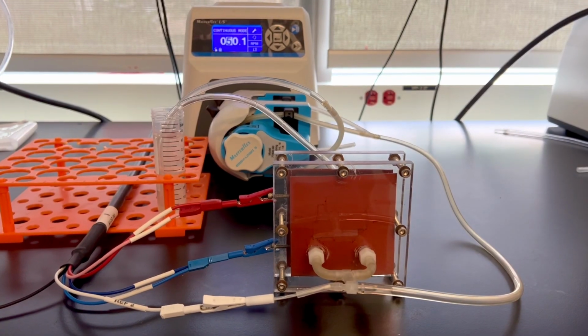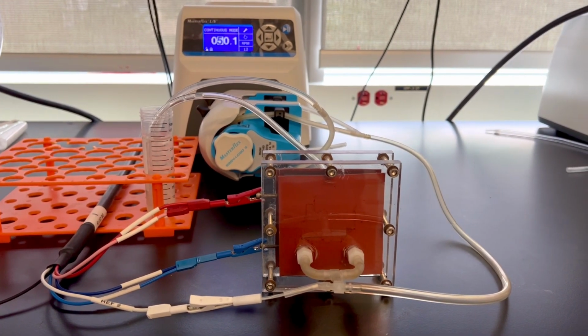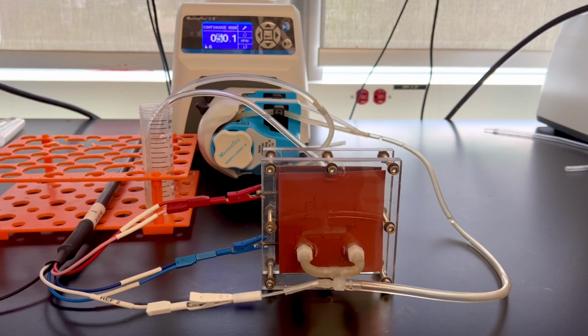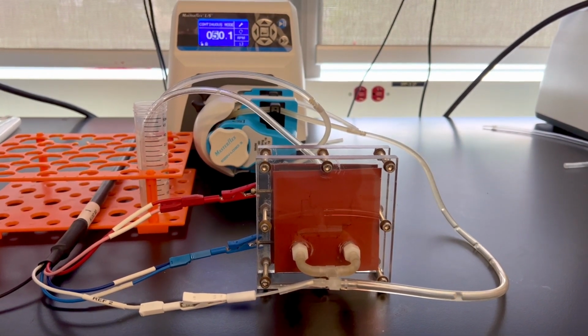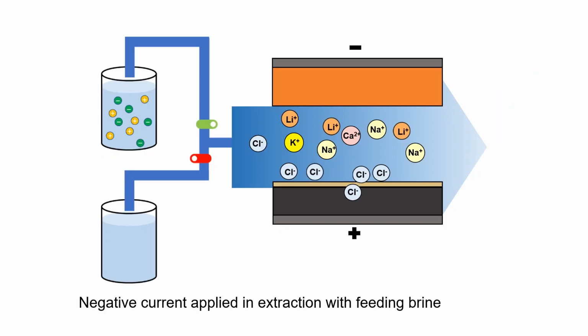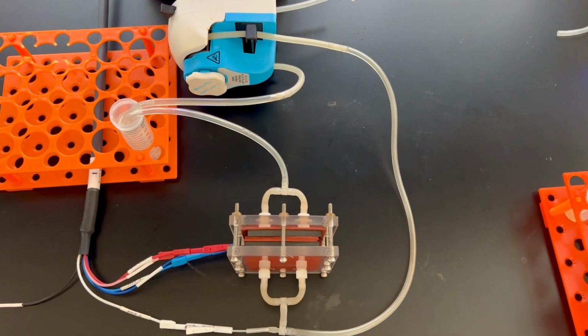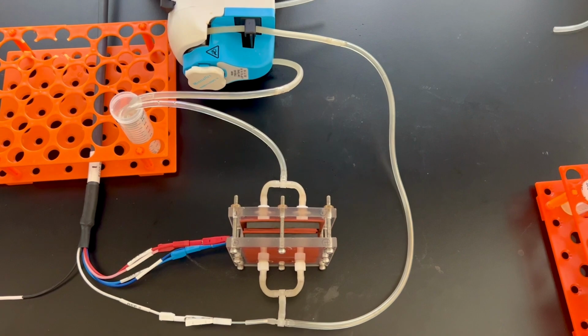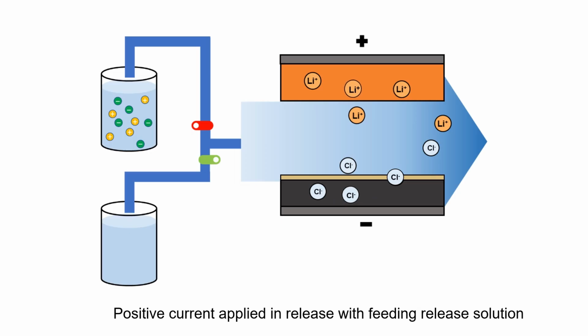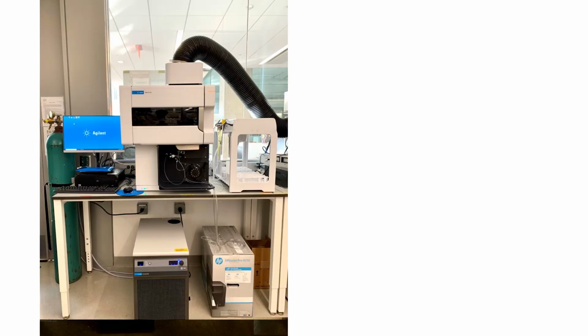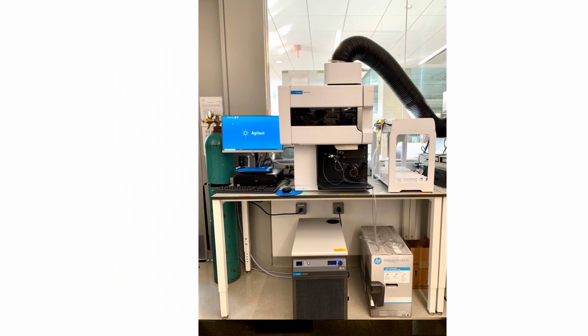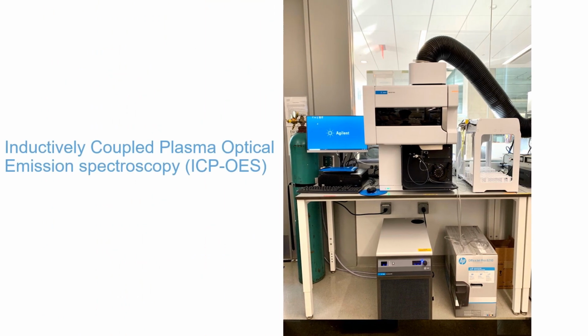Salton Sea geothermal brine was fed into the extraction cell with a continuous flow. Extraction of lithium began when we applied a negative constant current. After extraction, we switched the feeding solution to the release solution and collected lithium chloride solution by applying a constant positive current. The lithium selectivity was determined by measuring cation concentration in the release solution by inductively coupled plasma optical